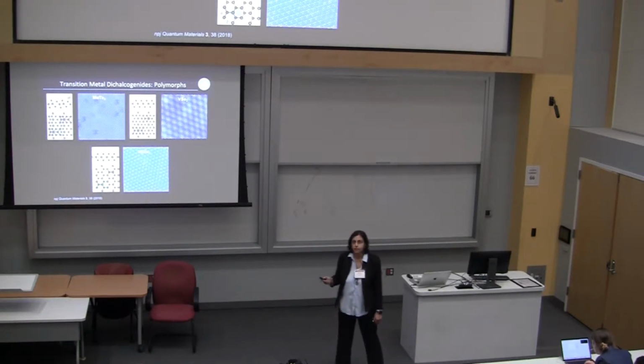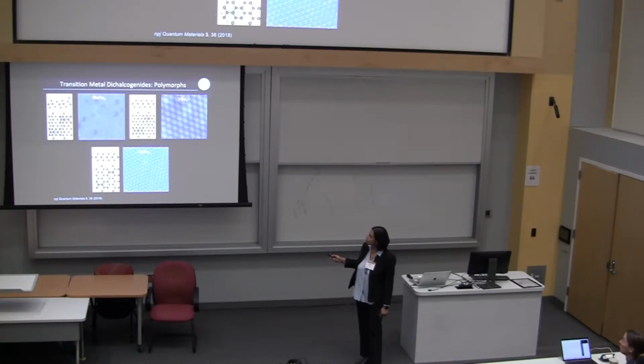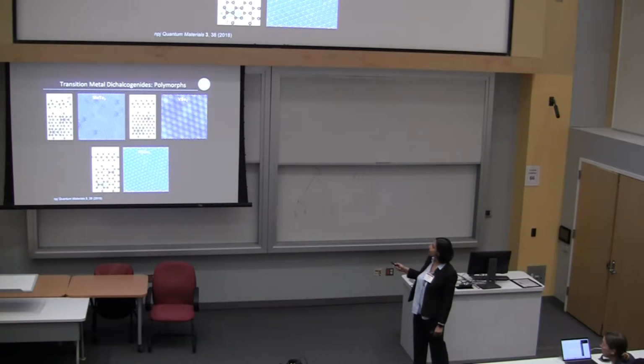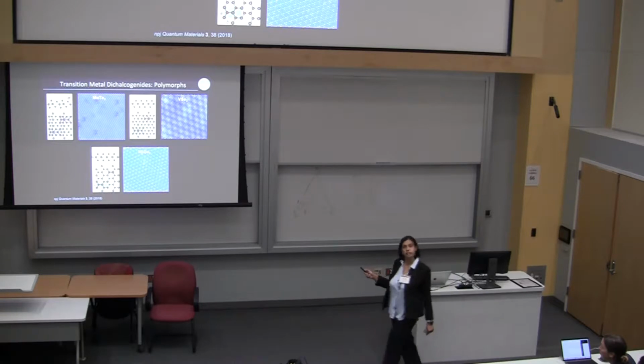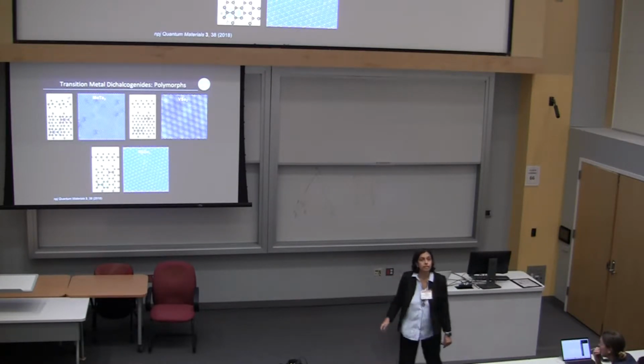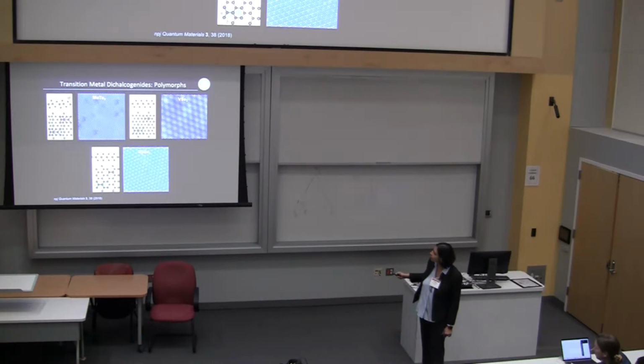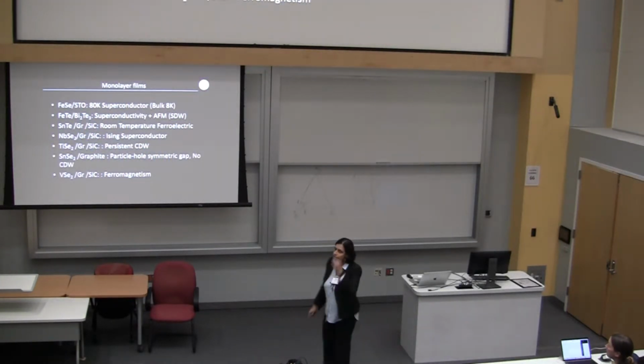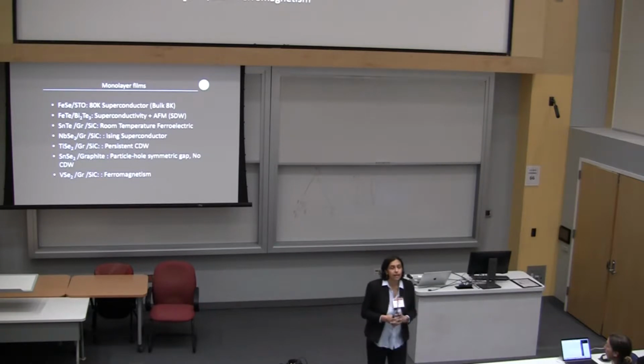So here are some STM examples. MoTe2 is a Weyl semi-metal. It crystallizes in the 1T prime phase if you play with it nicely. And you can see in STM it has these stripes which correspond to these up-down arrangements. The vanadium diselenide, this is a thin film, actually, or a bulk crystal in the 1T phase, and it has a charge density wave. So you can see hexagonal arrangement of atoms. Superimposed on that is a CDW. Niobium diselenide is 2H, and if you could remove the CDW from these two, they would look identical, actually. But niobium diselenide also has a CDW, and that's what you're seeing here. Okay. So that's just a brief overview of why transition metal dichalcogenides are so interesting.